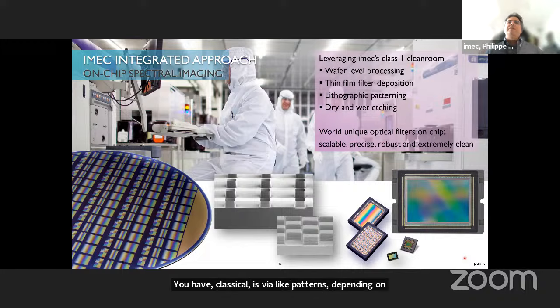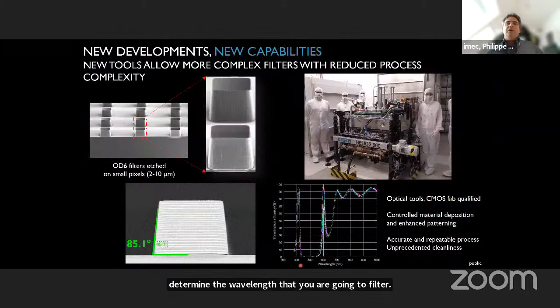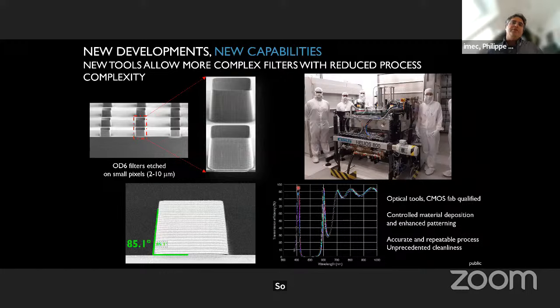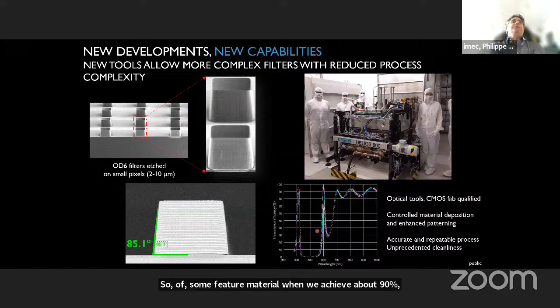Depending on the wavelengths that you want to sort, we apply different kinds of processes. And the control on all the layer thicknesses is extremely important because the physical thickness is going to determine the wavelengths that you're going to filter. So here is a classical example of a filter material where we achieve about 90% transparency at 400-something nanometers. You can see this is a typical layer stack that is being used.